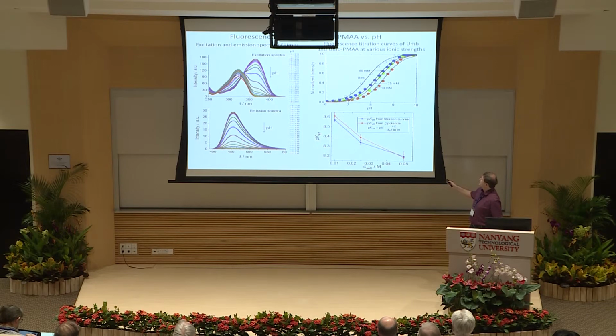And again, there is screening. If we take various concentrations of sodium tetraborate at the beginning, the higher the concentration, the smaller the shift of the pK because of the screening of the interaction of H+ with the polyelectrolyte chain.